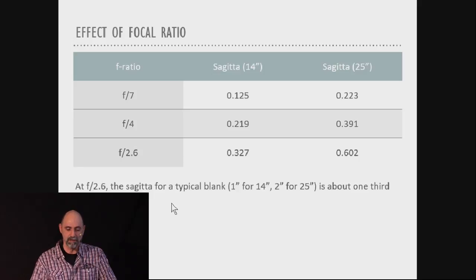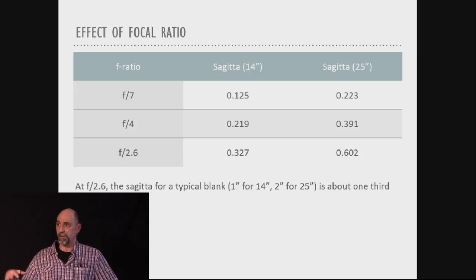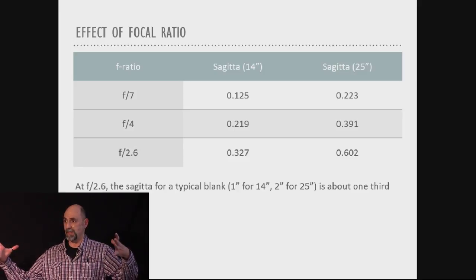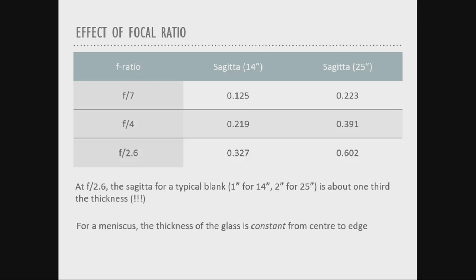So at f2.6, if your typical blank is going to be 1 inch for a 14-inch mirror or 2 inches for a 25-inch mirror, you're looking at about 1/3 of the thickness of your blank being carved away by the curve. What that means is that if you've got 100 pounds of glass and 1/3 of it in the center has been carved out, that leaves 2/3 there. So it's going to totally mess up the thermal properties of that glass, as well as structurally. You're basically making it considerably weaker there. So all of these things kind of compound. If you're looking at a large aperture, you can't actually fabricate a fast mirror without having a whole bunch of other complications. For a meniscus, however, again, think contact lens, the thickness is the same for the entire length of the curve. So basically the mirror is curved front and back so that it's of uniform thickness.